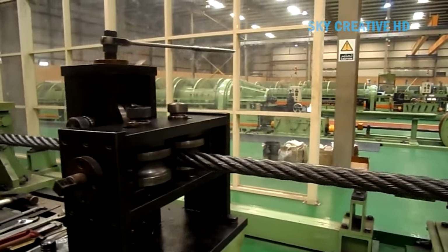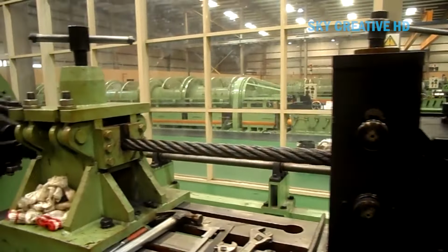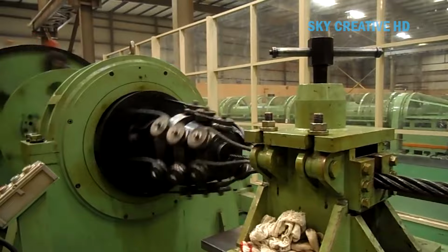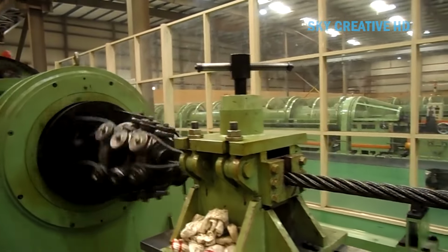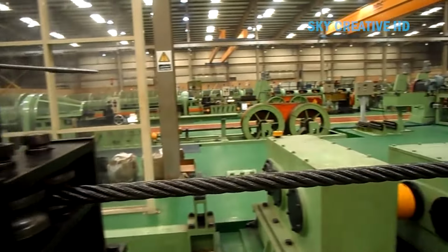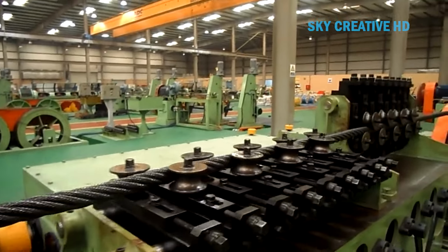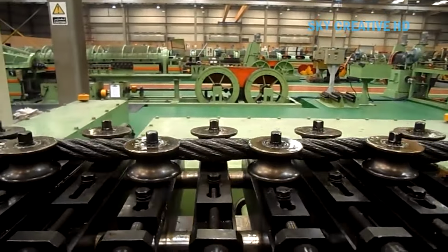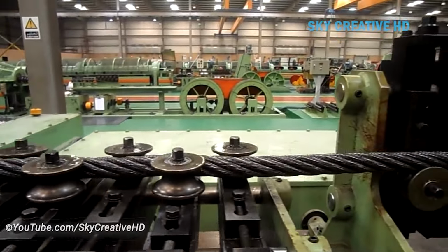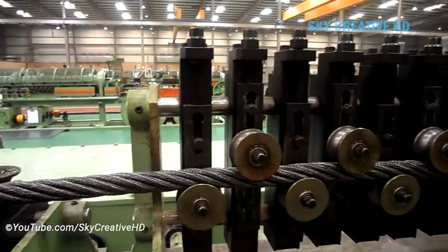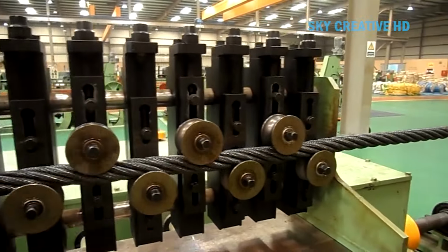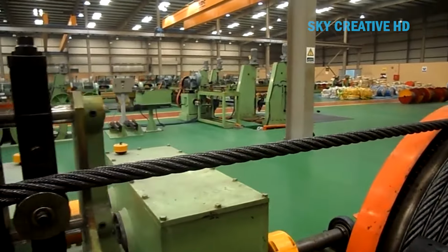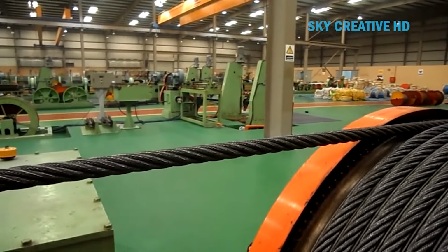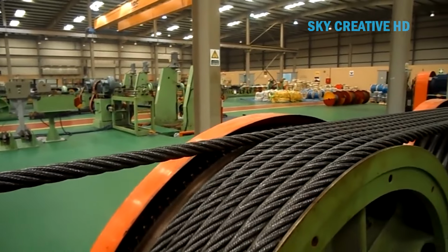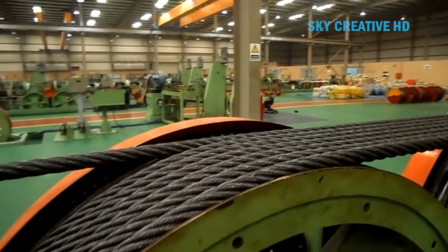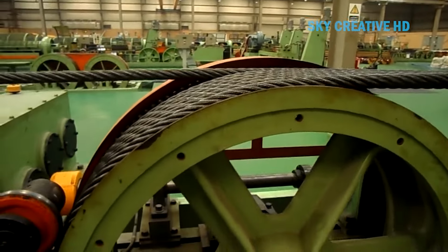Each pass through a die work hardens the steel, increasing tensile strength to over 2,000 megapascals. That's stronger than most structural steels. Between passes, the wire travels through cleaning tanks that remove scale and apply lubricants for the next reduction. Next comes stranding, where individual wires combine into strands. A specialized stranding machine called a tubular strander holds multiple wire spools. As the machine rotates at high speed, sometimes 80 RPM, the wires twist together around a center wire, forming a strand. The lay length, or distance for one complete twist, is carefully controlled.